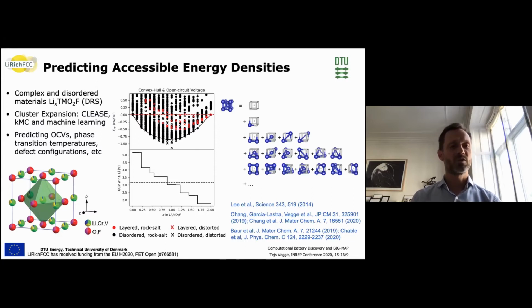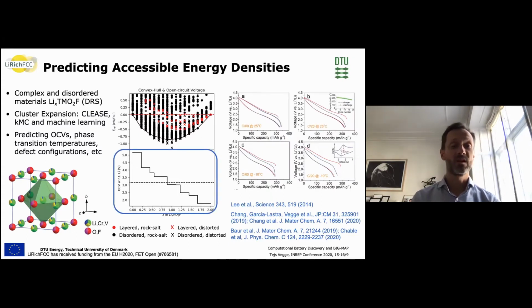So what Jin-Yun Chang and colleagues developed was a combination of a cluster expansion method called CLEASE with kinetic Monte Carlo and machine learning that allows us to predict the performance of oxyfluoride materials, in particular the lithium vanadium oxyfluoride materials, predict open circuit voltages, phase transition temperatures, even defect configurations as a function of lithiation, such that we can assess what is the accessible energy density that we can use for repeated cycling.